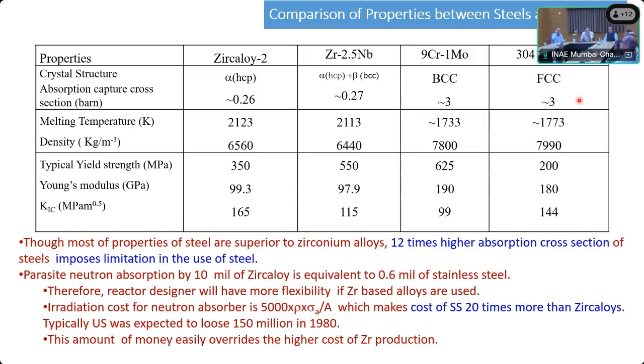So if you do the back of envelope calculation, you will find it gives you two advantages. One, the thickness of the tube allows the designer to play along without compromising too much on the neutron economy. Second, on the overall irradiation cost of the neutron, because the steel becomes so radioactive, it will be very difficult to handle. So if you calculate all these things, then you find that the higher cost of zirconium production can be overridden by this.